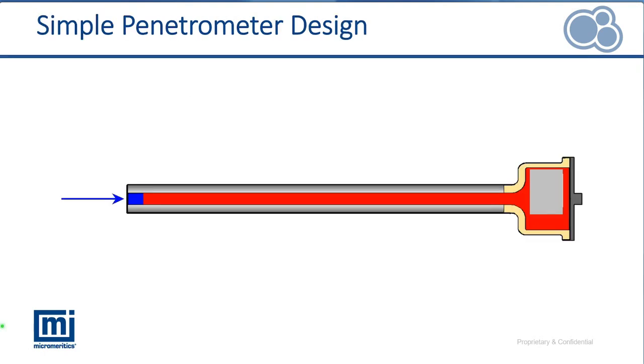Now, earlier I showed you some examples of penetrometers. Here we see the schematic of a penetrometer, because I want to talk a little bit about how we do in fact determine the intrusion volume that's taking place. We see here the penetrometer with a cutaway section on the capillary stem. We've actually cut a section away here so you can see the mercury that's inside filling the stem. We see the sample actually floating in the mercury, because usually the sample has a lower density than the mercury. Sitting here, this gray bit's our sample.